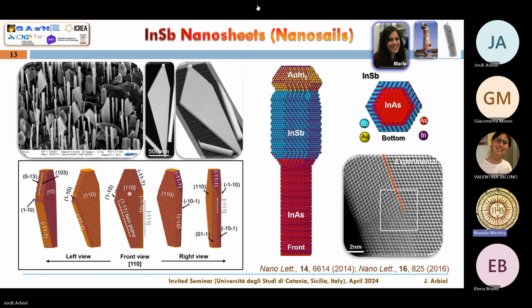But then let's investigate what happens in the nanosail. Why is so different if we grow in the same batch and exactly with the same conditions? What we found is that in every single nanosail, exactly at the interface, we could find a twin boundary. So there is a kind of nucleation misfit here in which a twin dislocation is appearing. And what this dislocation was creating, it's a breaking of the symmetry here. So this 110 facet was broken, and instead of that, you change with this twin boundary, and instead of having a perfectly unpolar surface, here you have a perfect polar surface and exactly terminated in the anion. So what this was doing is breaking the symmetry and allowing the material to grow to this side as well. And this was the reason why you could create these really nice nanosails.